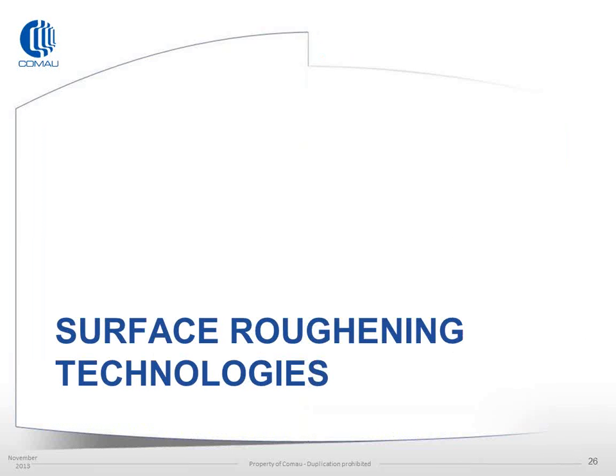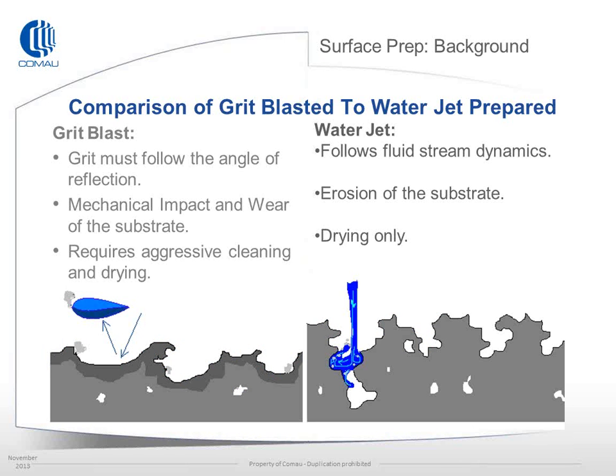In terms of surface roughening technologies, this is really a package that everyone's looking for. Most customers, some of the early adopters have developed their own. Some of the new to the market are looking for assistance. Some of the first technologies that went into the market are grit blasting, which is one of the oldest surface prep technologies. It creates a very random and rough surface. It's difficult to measure and count and identify the quality of the surface without an adhesion test. One of the more major issues for production is the cleanliness. Grit blasting tends to create a lot of statically charged fines, and these tend to adhere to the surface quite well and make it difficult for cleaning and coating afterwards.